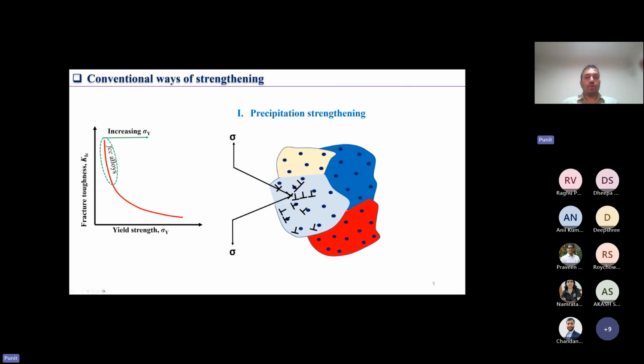So if we want to develop FCC alloys, the strategy we need to have is that we want to increase their yield strength without affecting the fracture resistance. So conventional ways of achieving this, the first one I want to highlight here, is precipitation strengthening. What you can do is put these precipitates inside the material, which can block the movement of dislocations, and you can increase the strength of the material.